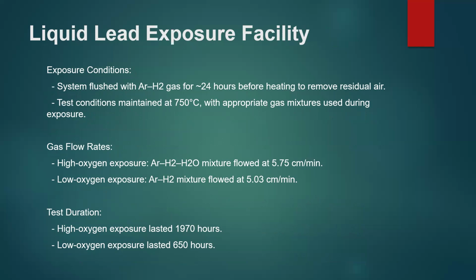This condition was maintained at 750 degrees Celsius with the appropriate gas mixture used during exposure. Gas flow rates: for high oxygen exposure, argon-hydrogen-water mixture flowed at 5.75 centimeters per minute, and for low oxygen exposure, argon-hydrogen mixture flowed at 5.03 centimeters per minute.